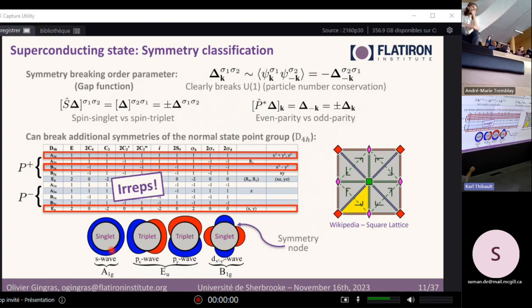So for a spherical Fermi surface, if you have a conventional superconductor where the gap is just constant everywhere, this projects on S wave, so we say it's an S wave, and because this is even parity, typically it forces it to be spin singlet. Here we have an example of a two-dimensional irreducible representation, Eu, which projects on px and py in a degenerate manner. Because this is odd parity, we will have a spin triplet state. And here we have the well-known state of the cuprates, what is thought to be the symmetry of the cuprates. This B1g state projects on dx² minus y² and is a singlet.